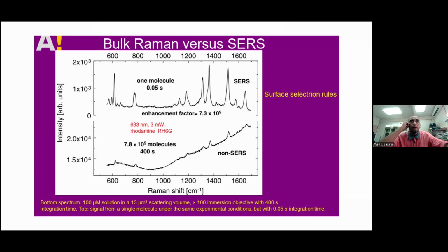One molecule of rhodamine will give you an enhancement of 7.3 times 10 to the power 9, compared to 7.8 times 10 to the power 5 molecules of rhodamine. So this is the enhancement factor. So one molecule can give you an enhancement factor of almost 10 to the power 9. So one molecule in SERS, the intensity is more than around 100,000 molecules of the same type of molecule without SERS. So this compares SERS to the normal Raman or bulk Raman technique. So that is the advantage of SERS compared to the normal Raman or the bulk Raman.